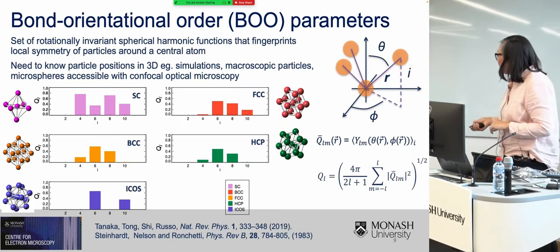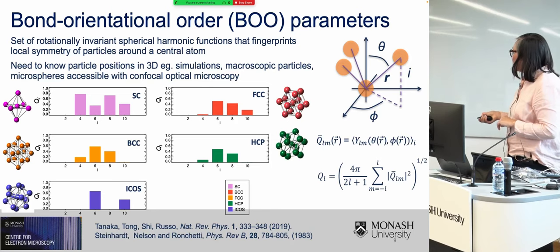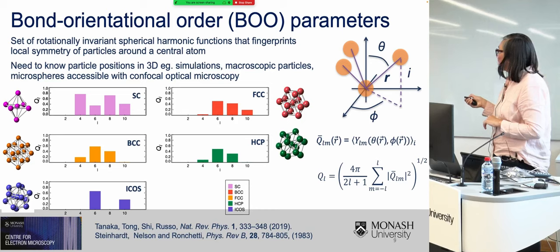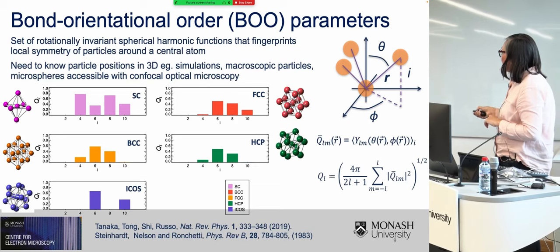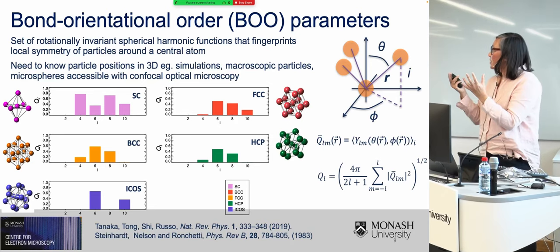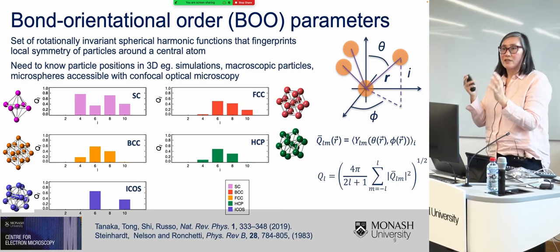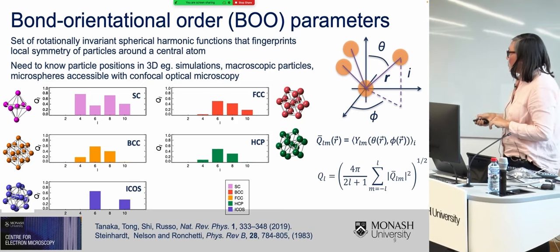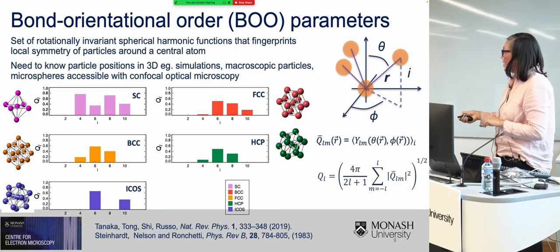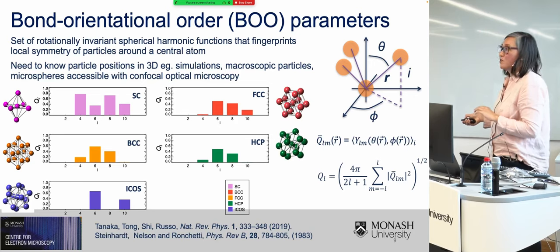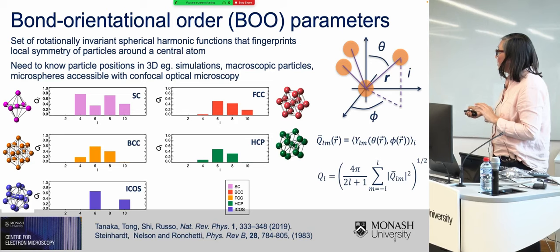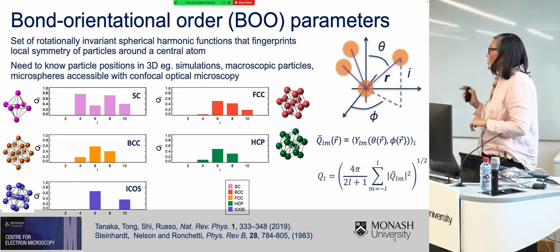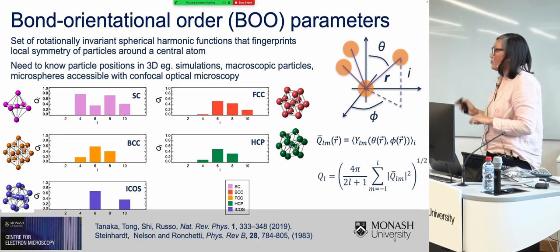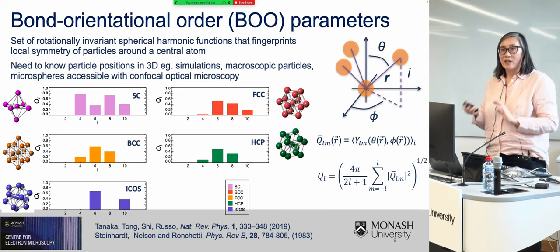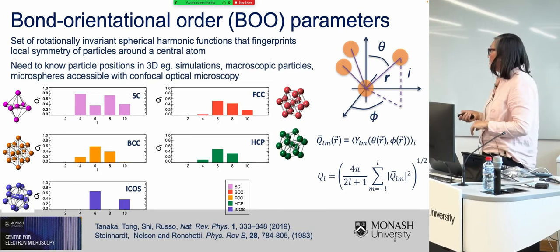So in 1983, Steinhardt, Nelson and Ronchetti introduced these parameters called the bond orientational order parameters. And these are simply the rotationally invariant spherical harmonic functions that fingerprint the angular arrangement or the symmetry of particles around a central atom. So here I'm showing these bond orientational order parameters for these different archetypal polyhedral types. And you can see that they're very strong fingerprints. They vary a lot depending on the different kinds of local symmetry. And it would be no exaggeration to say that these BOO parameters have been used in thousands and thousands of studies on structure in liquids and glasses and semi-ordered systems.